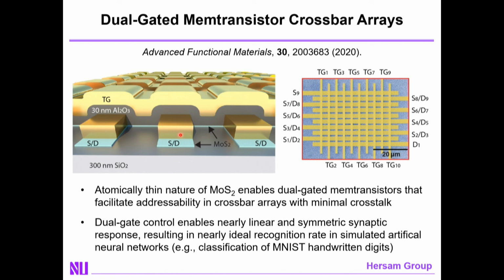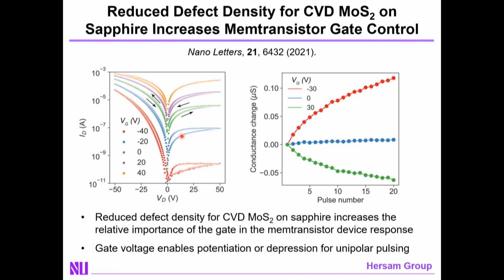Additionally, when you have 2 gates, you now have further tunability over the synaptic response, which can be useful in a variety of classification algorithms. Additionally, I want to stress that this behavior depends very much so not only on the grain size of your material, but also the defect density that's present in your material.